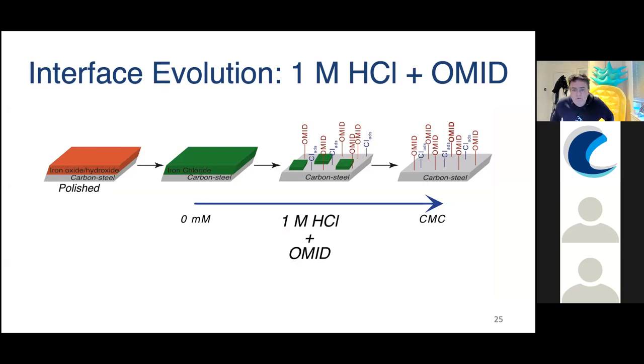So this shows you how we think this interface evolves. I've already talked about it being two singly protonated species, but as regards the substrate, we start on the left-hand side with our polished substrate, where we have an iron oxide hydroxide layer. In 1 molar hydrochloric acid without any OMID, there's an interface, the oxide hydroxide is replaced by a thin layer of iron chloride. And then as you go towards CMC, there's no iron chloride left and the molecules are adsorbed, the OMID in these two differently singly protonated states along with adsorbed chlorine atoms. So this is what the interface looks like.